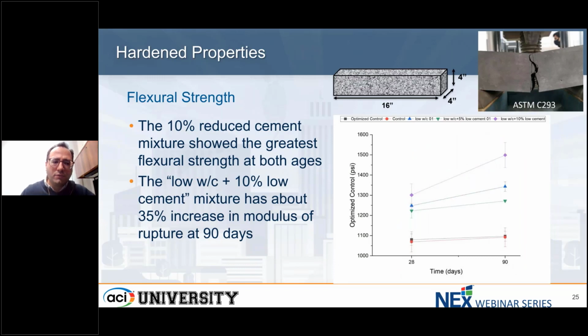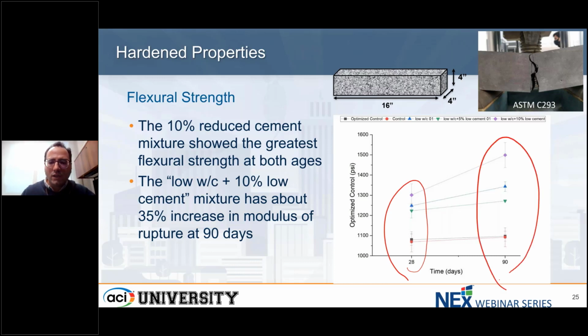The other mechanical performance we tested was flexural strength. We took these beams, 4x4x16 inches, tested based on ASTM C293. And these are the results after 28 days curing and after 90 days curing. So you see again a similar trend compared to compressive strength. The optimized system with low cement is performing better than the other systems, and we see almost 35% increase in the modulus of rupture after 90 days of curing.